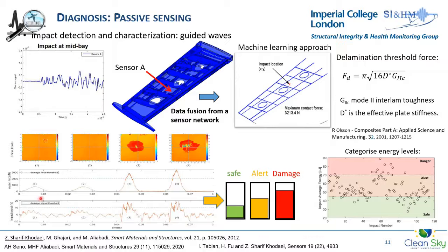So here you can see at the bottom the C-scan results of 4 different plates manufactured exactly the same with different layup, and they've been impacted with different levels of energy. Some of them are low, as you see here, where the impact force has not resulted in any damage, and some of them are high, where you can see that delamination has occurred between the plies. When we compare the contact force to the maximum amplitude of the recorded signals, you can see that there's a direct correlation between the amplitude of the signal and the threshold, which you see here as the dotted line, which is the threshold for initiation of damage.